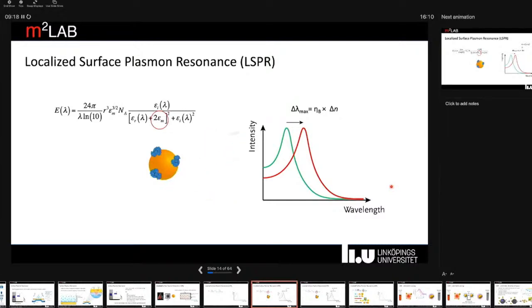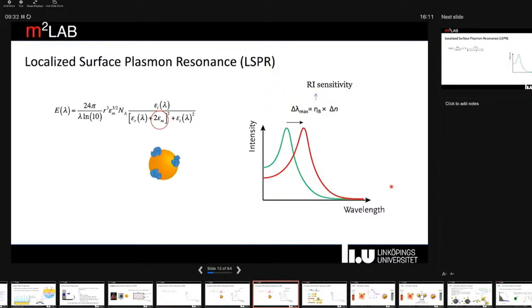So essentially what we are detecting here is changes in refractive index, just similar to SPR. And then we also have this term here in this equation that determines the magnitude of this SPR shift, or plasmon band shift. That's what we refer to as refractive index sensitivity. And we'll come back to that during this talk quite a lot, what we can do to essentially improve this, to increase sensitivity of sensors based on LSPR.